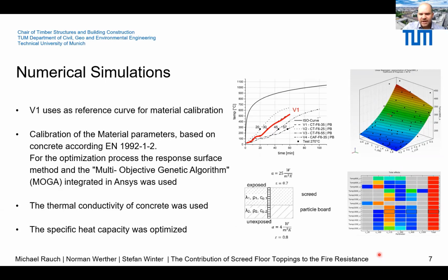To do numerical simulations, material parameters for screeds are necessary. Starting from the material parameters for concrete, according to EN 1992-1-2, the material parameters were calibrated based on test number 1. You can see it here in this diagram. The multi-objective genetic algorithm integrated in ANSYS was used to optimize the material parameters for screeds based on the response surface method. Here you can see the response surface for the temperature evaluated at 1,800 seconds.